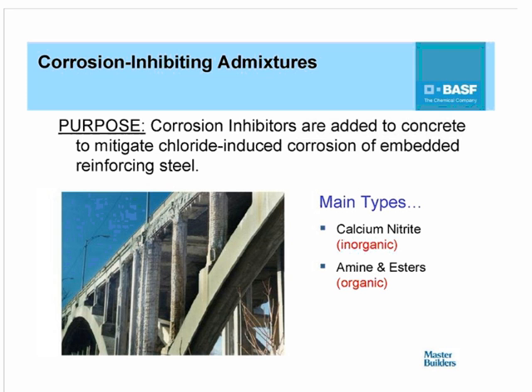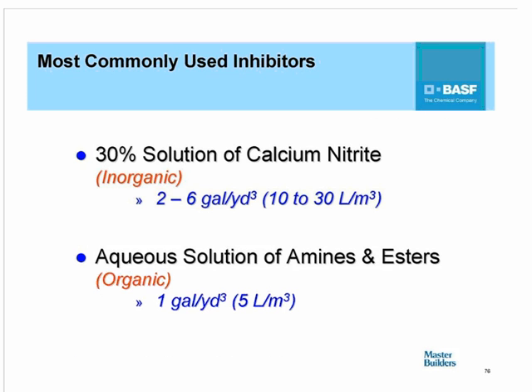The next group of durability enhancing admixtures will be the corrosion inhibiting admixtures or corrosion inhibitors, which are added to concrete primarily to mitigate chloride-induced corrosion of the reinforcement. Now, the main chemistries or the primary chemistries that are used in the marketplace are a 30% solution of calcium nitrite, as well as an organic solution of amines and fatty acid esters. Now, these materials work differently.